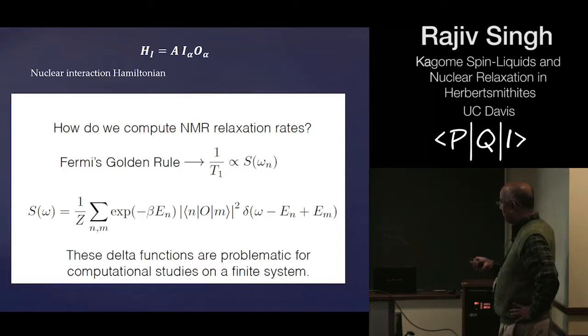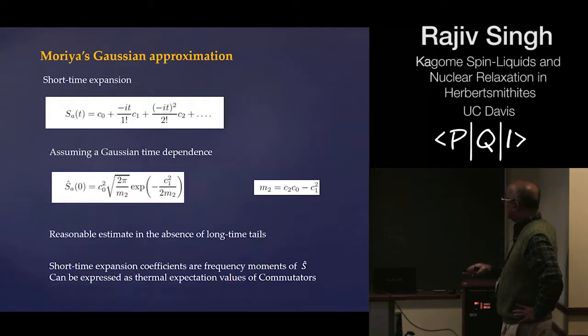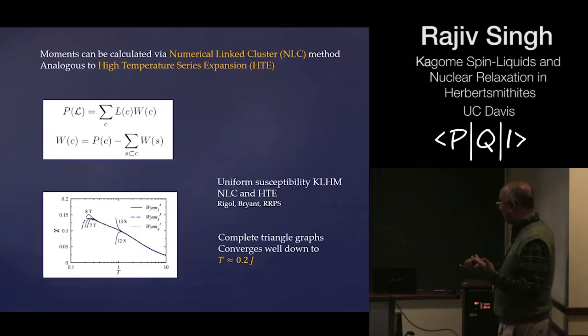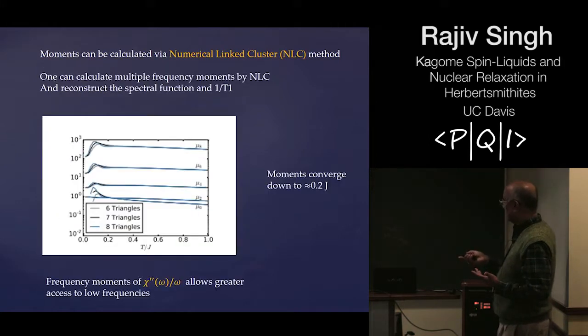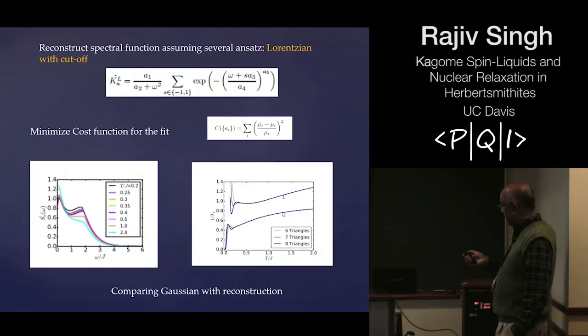That becomes a very challenging problem because of these delta functions over here, and the energy levels keep shifting from one cluster to another. So partly we use Moriya's Gaussian approximation, which one can do in the thermodynamic limit, but we can also calculate more frequency moments, basically by using computational methods such as the numerical linked cluster method. Then we have to assume some kind of an appropriate line shape, which we assume is a Lorentzian, but then we also have to assume a cutoff because all frequency moments are finite. So the system cannot simply have a Lorentzian line shape.